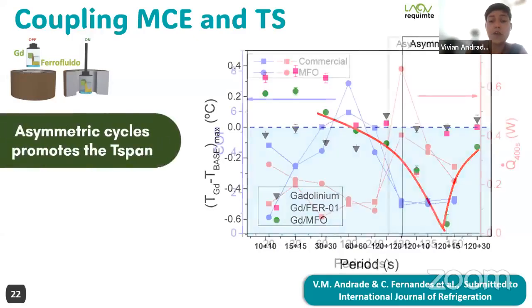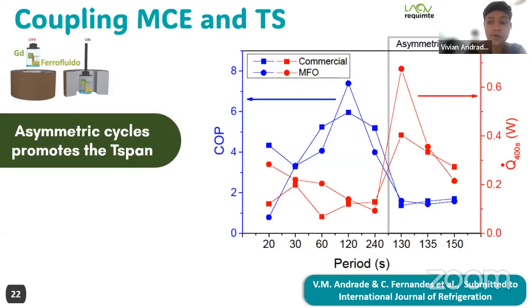But we also need to look at the coefficient of performance and also the cooling capacity. We had a cooling capacity of 0.7 watts. And if we normalize this by the amount of material that we have, of 7 grams, if we compare with the efficiency of the air conditioning, we achieved almost double their performance. We don't look only at the temperature span, we also need to look at the other key parameters.